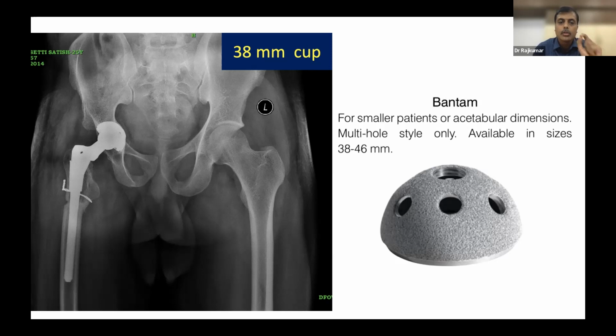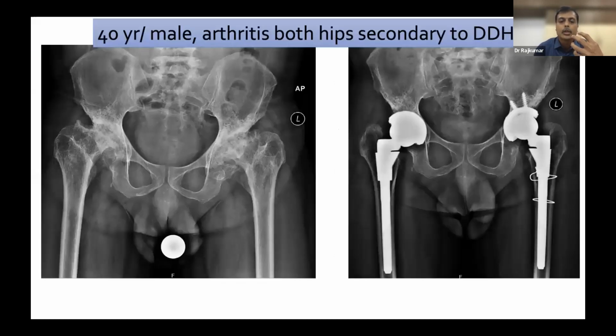To know this, you need to template and arrange, because you will not always have these bantam cups available on the shelf. So the 38 mm cup is the cup which I have used here, and you have to arrange it beforehand. Even though this is also a hemispherical cup, and the coating is a Porocoat coating, it takes only a 22.2 mm head.